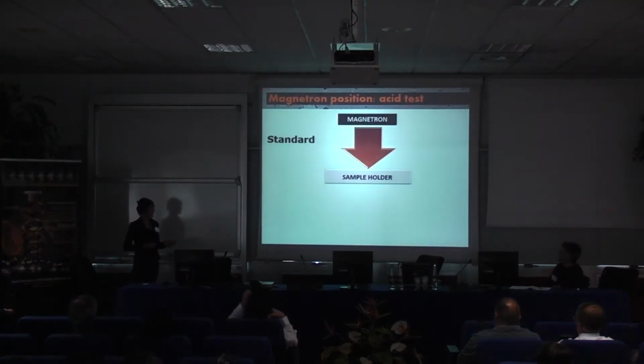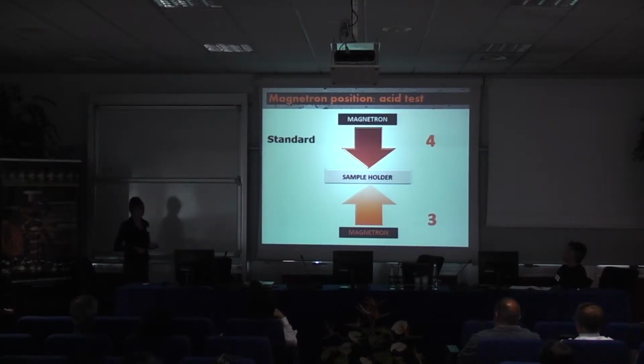When we reversed the standard configuration, when the magnetron is up and the sample holder is down, to the reverse one, we obtained a decrease of porosity correspondingly. This is probably the best known method of decreasing porosity everywhere.